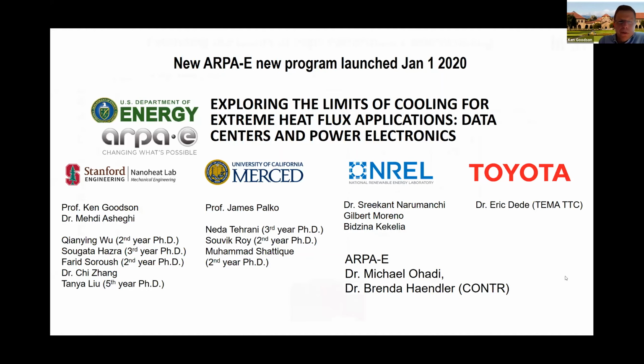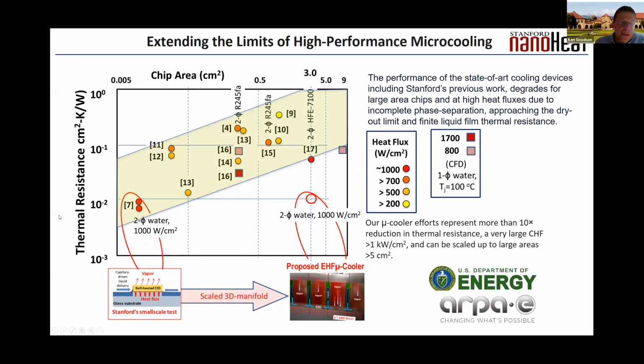And this program launched January 1st. And if you look at the thermal resistance as a function of the chip area, what we did with DARPA was achieve a very, very low thermal resistance for a huge heat flow of 1,000 watts per centimeter squared. And what we're trying to do now is take these approaches and do it over a wide area device that would apply for a data center chip or for power electronics chip. So to increase it to 3 centimeters squared from a fractions of a centimeter squared. And so this extension is an extension of technology, not of physics. It's an extension where we have to deal with the fluid routing and the complexities of integration and thermal expansion mismatch, and all sorts of things. And this is what we're doing with ARPA-E.